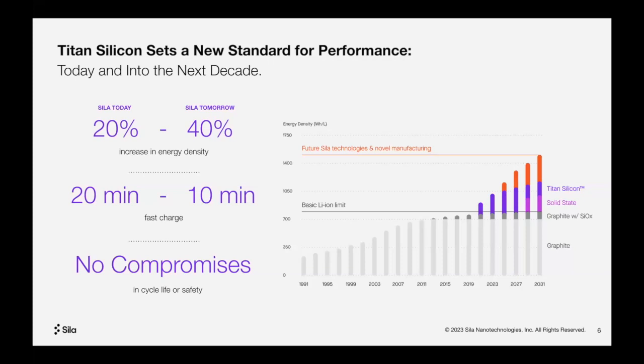The other thing that's really key here is the fast charge, where today we're getting about a 20-minute fast charge. And when we speak of fast charge, that's 10% state of charge to about 80%. And in the future, we expect to get that down to about 10 minutes. And the beauty of this is that you don't have to compromise anywhere else. You're not compromising in cycle life or safety or in temperature performance or anything like that. We're able to maintain all the other metrics and just improve these two.